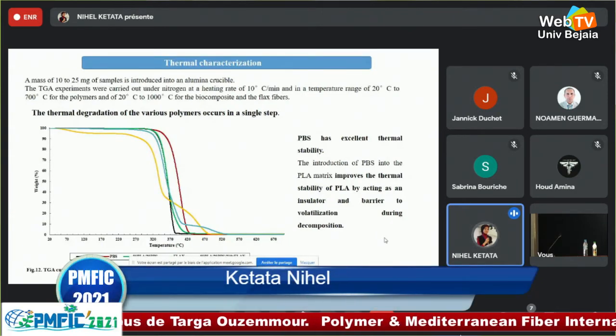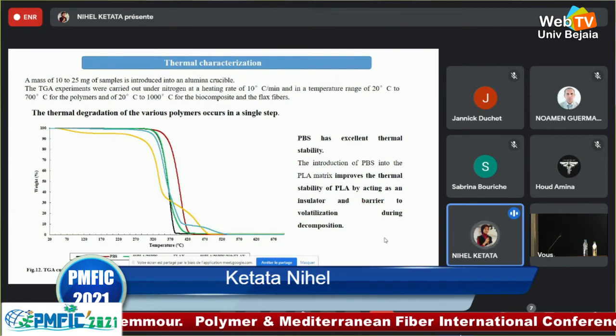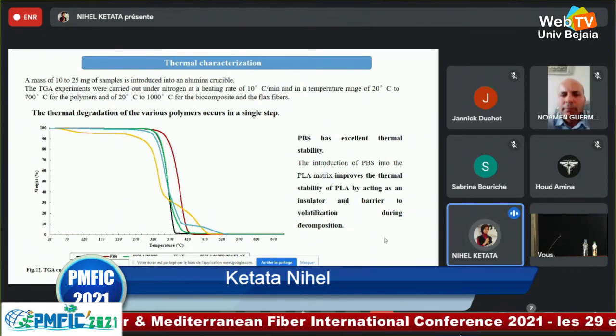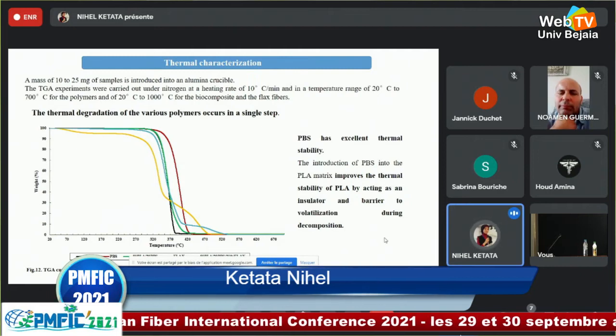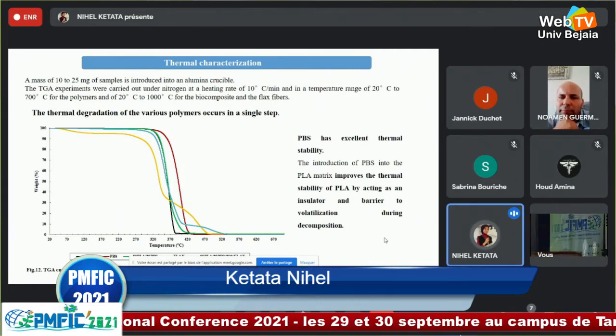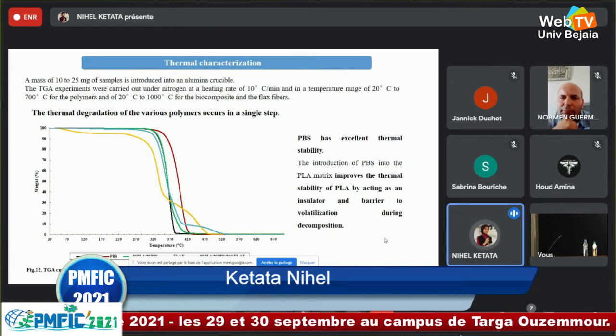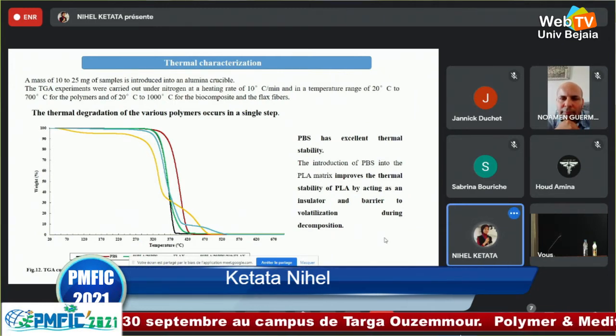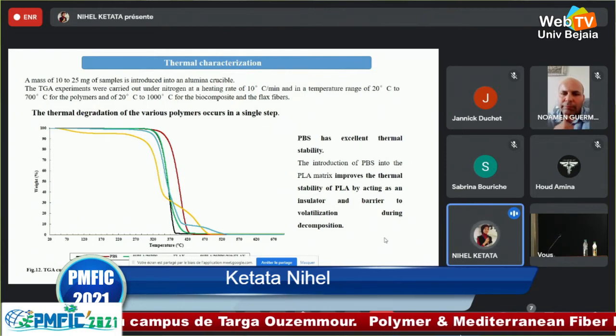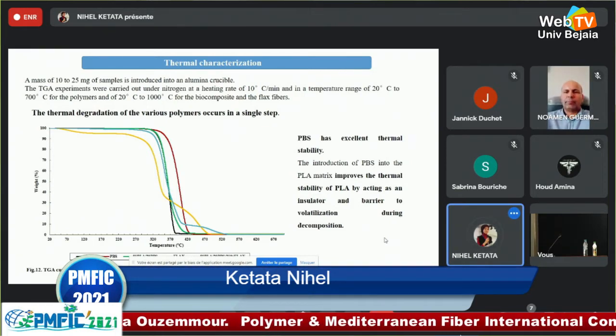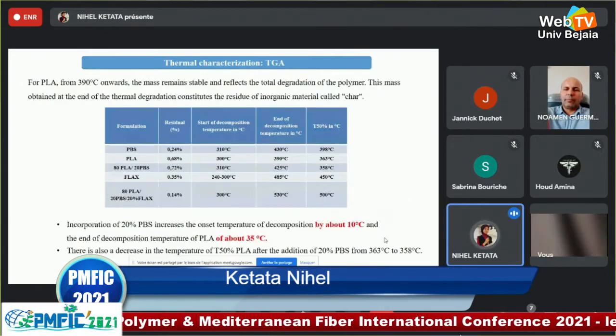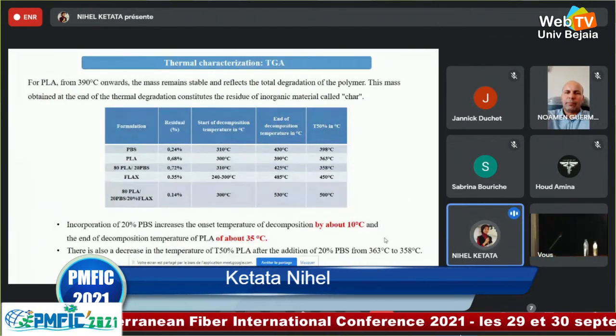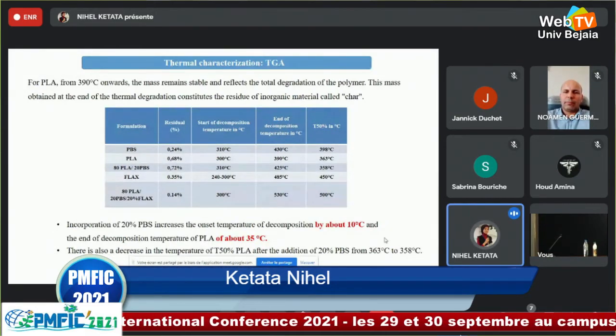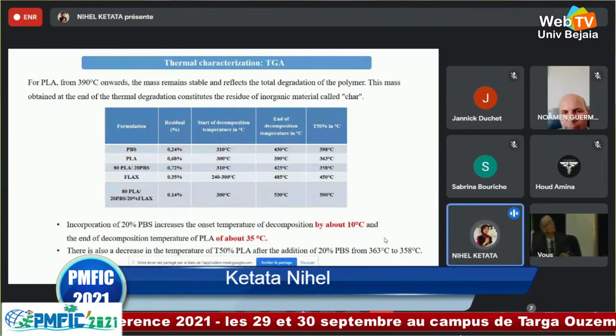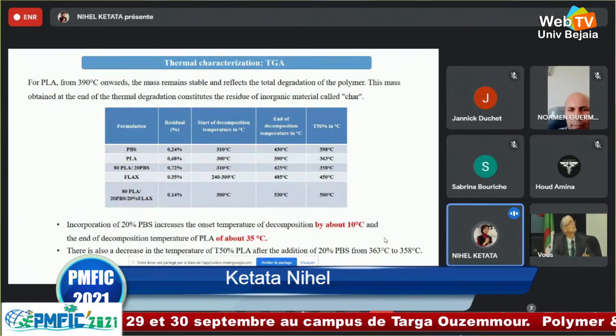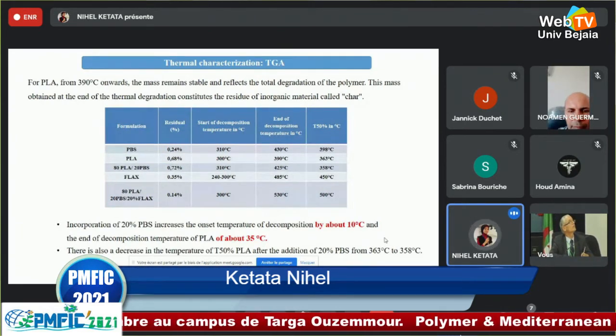Moving now to the thermal characterization. For the four formulations and the flax fiber, the results show that the PBS had excellent thermal stability. Also, the introduction of PBS into the PLA matrix improved the thermal stability of the mixture compared to PLA only. In comparison, 20% of PBS increased the onset temperature of decomposition by about 10°C and the end of decomposition temperature of PLA by about 35°C.